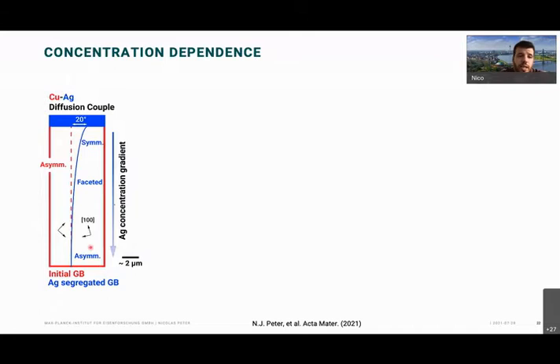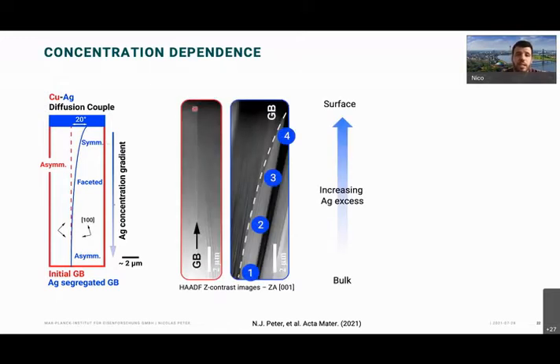And what we could find, I wrote it down here already, is we have an asymmetric boundary, we have a faceted boundary, and then we have a symmetric boundary. So the boundary changes depending on the silver concentration that we have. And this is shown here. This is the initial boundary, which is straight. And then at the end, it curves away towards the surface after the experiment. And of course, these are not rotated. These are, of course, in the same orientation.